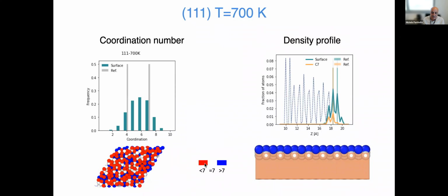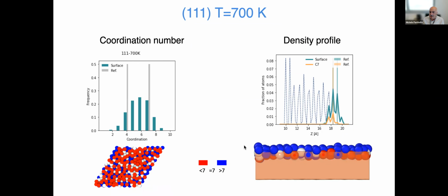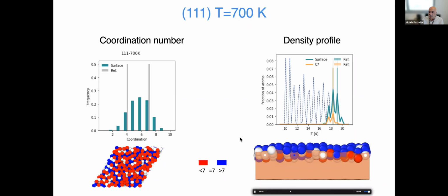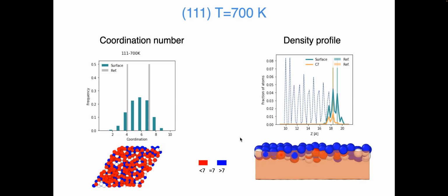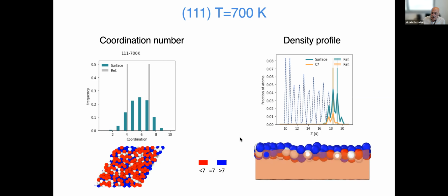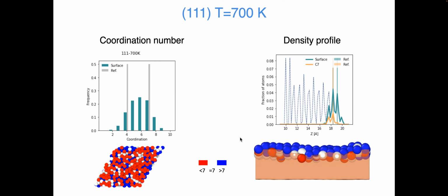We color the atoms according to their coordination number. And you can see also in the direction perpendicular to the surface, there is a lot of action. From the fourth layer on, the lattice is more stable. It's just a phenomenon confined to the first few layers.